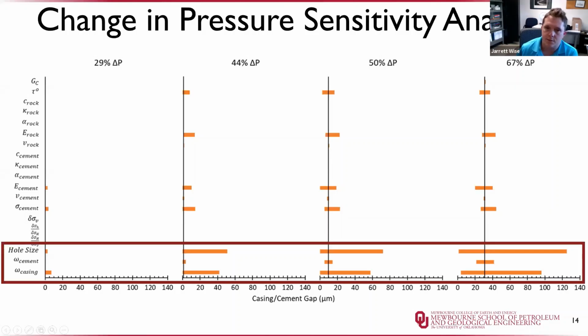So looking at the trends from this sensitivity analysis, we see that hole size and casing thickness are the two main parameters that have the largest effect on microannuli size when you change the pressure. The interesting thing is, especially in the cement community, everyone wants to look at additives in cement to basically hold up integrity. But from this analysis, we see that really the additives in cement, like the Young's modulus and Poisson's ratio, aren't having as dramatic of an effect.